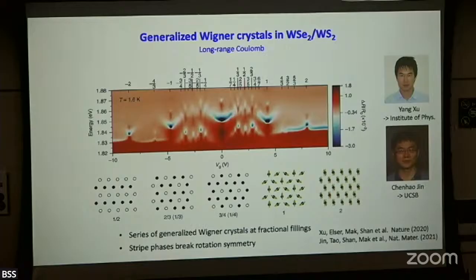Light reflectance. Yeah. Is there any reason, or maybe you did do this, like infrared reflectance, an experimental challenge for looking at the Drude peak and how it evolves with filling? Yeah. So this is all in the visible, right? Infrared is a little bit difficult because the spot size is very big, and for Drude we're talking about a spot size 300 times bigger than your sample.